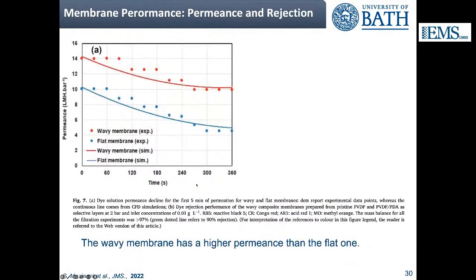Okay, so let's look at some results. So this is the pure water permeance. The dots are experimental data, and the solid curves are from computational fluid dynamics simulations. So time zero is the pure water permeance. And again, you see that the wavy membrane in red has a higher starting permeance, or pure water permeance, than the flat membrane because of the higher surface area within the same footprint. And then here we use some dyes, and you can see that the permeance decreases because of fouling.